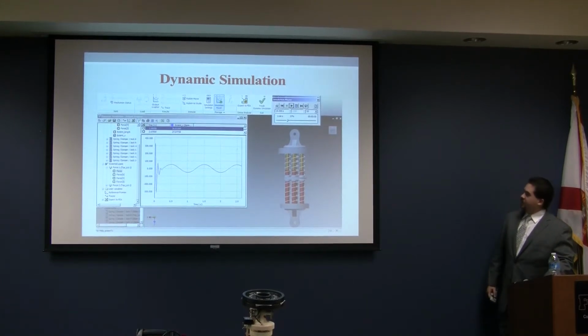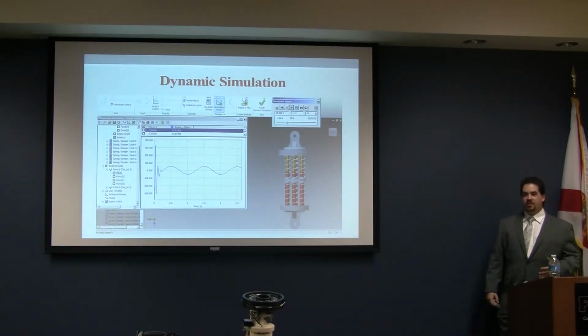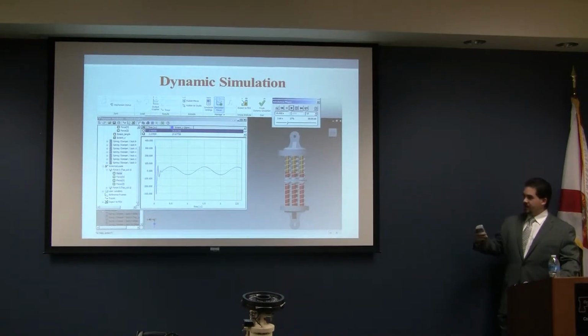And as far as dynamic simulation is concerned, we did perform one, but once again, because nitinol is a dynamic material, we couldn't perform one at martensite and austenite, so we treated everything in the austenitic state, and we performed a simulation in order to take that into account.